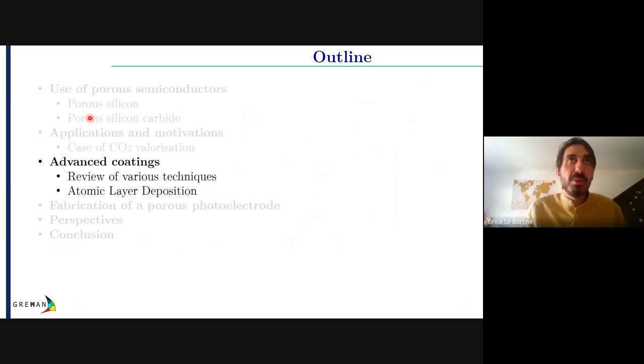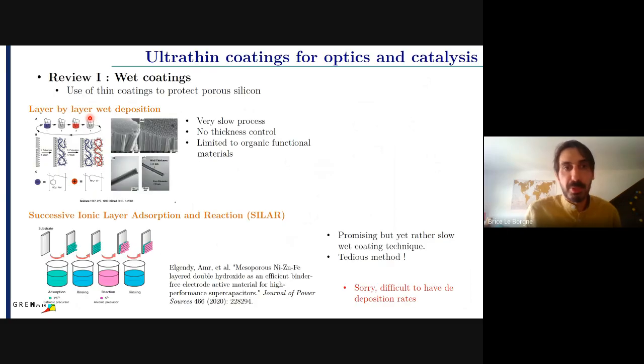So I'm going to talk about the possibilities we have to perform these coatings. I'm going to do it quickly and not enter into the details, but it's possible to coat porous substrates with wet coatings. One of the techniques is layer by layer deposition. You might know it. It's just a dipping process, and you can do it layer by layer. So it's very slow, unfortunately. It's very difficult to control the thickness. I guess specialists can do it, but it's not straightforward. And it's unfortunately limited to organic materials, which restrains the possibilities a bit.